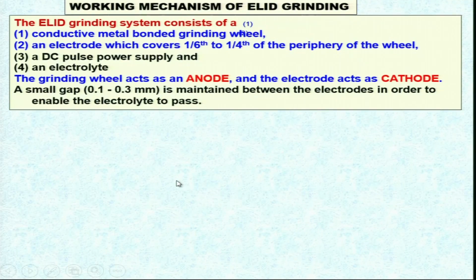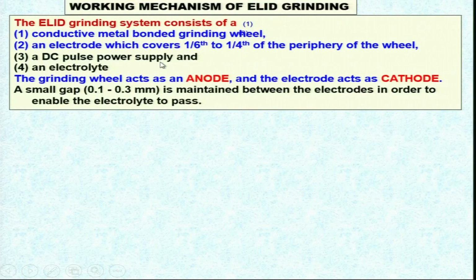Working mechanism: you can see here the ELID grinding system consists of a conductive metal bonded grinding wheel, we have already seen it, and an electrode which covers 1/6 to 1/4 of the periphery of the wheel. That electrode was there which is covering 1/6 or 1/4 of the periphery. I hope you remember this is used. This electrode is making the electrolytic reaction take place, so that the oxide layer is formed, and then that oxide layer is slowly removed and fresh abrasive particles protrude over there. A DC pulse power supply is there which can be converted into pulsed power, this AC also in some cases, and an electrolyte is there.